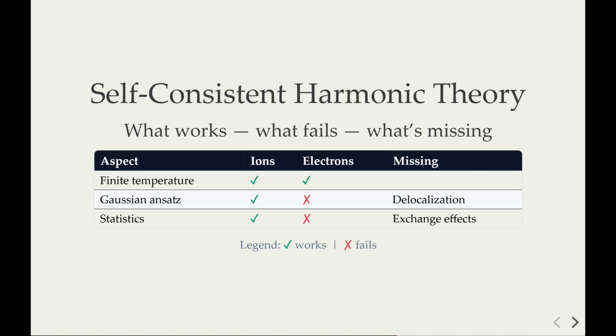The other issue, probably even more crucial, is that electrons have very important exchange interaction, while for ions exchange interaction is usually negligible. So we need a way to introduce into the self-consistent harmonic theory a way to go beyond the Gaussian ansatz and to introduce the Fermi-Dirac statistic, essentially. These are the major limitations that hamper direct application of this theory to electrons.